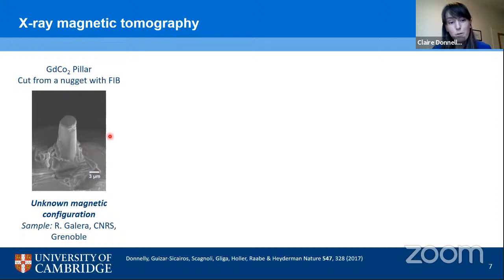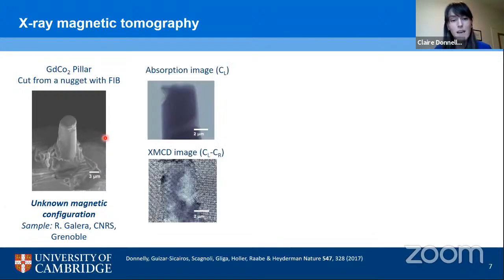And so what we first of all do is we go to two-dimensional magnetic imaging. We measure these XMCD images, so first with single polarization and then taking the difference between the two at the gadolinium L3 edge, because this provides us with the strongest XMCD signal in these higher energy X-rays. And we can see with the single polarization image, it's very much dominated by the electronic contrast. This makes sense because the magnetic contrast is very weak.